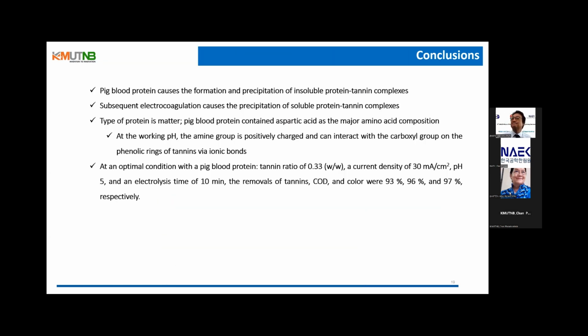Yes. In conclusion, blood protein caused the formation and precipitation of insoluble protein tannin complexes. Subsequent electrocoagulation caused the precipitation of soluble protein tannin complex. Type of protein matters. Pig blood protein contains aspartic acid as the major amino acid composition. So at the working pH, the amine group is positively charged and can interact with the carboxyl group of the phenolic rings of tannins via ionic bonds.